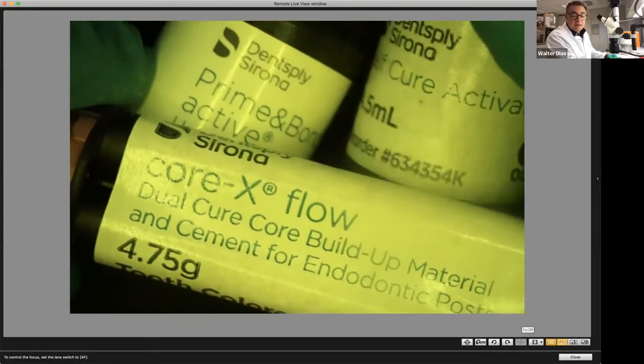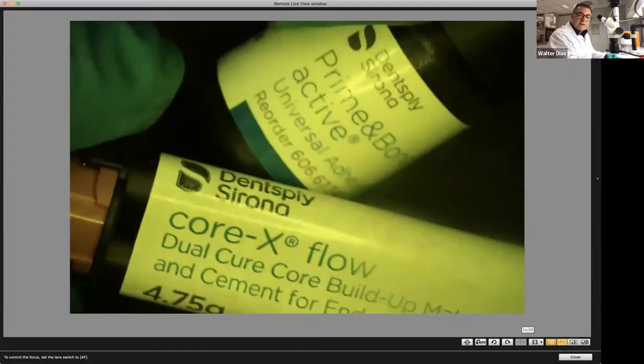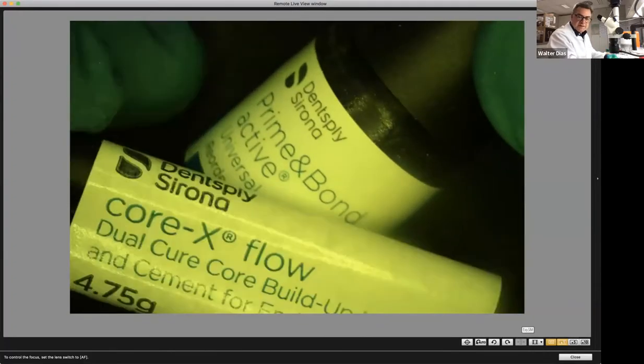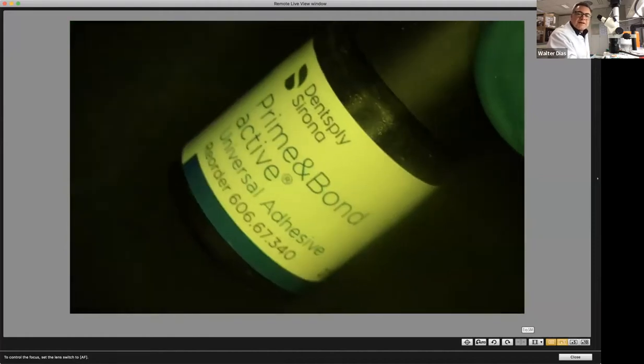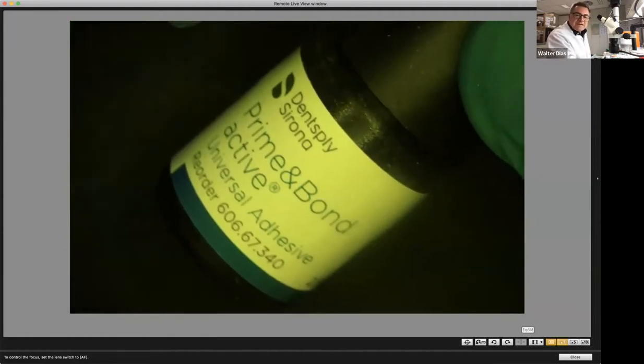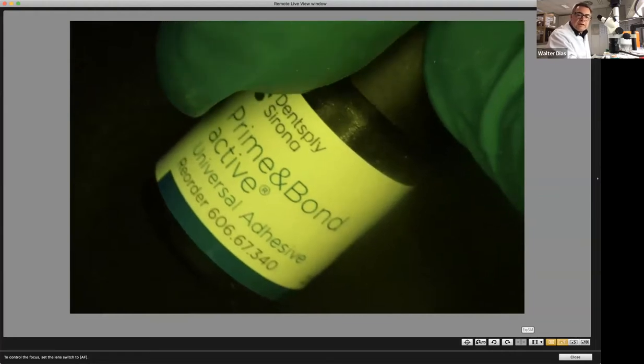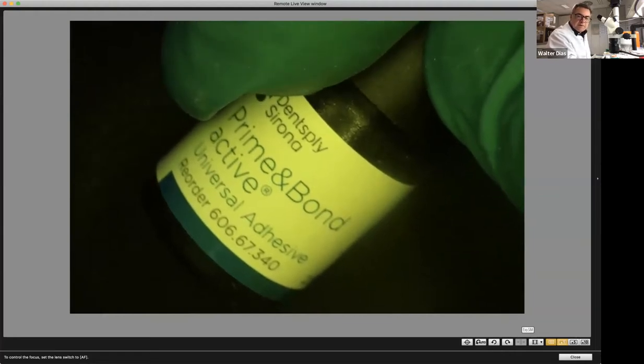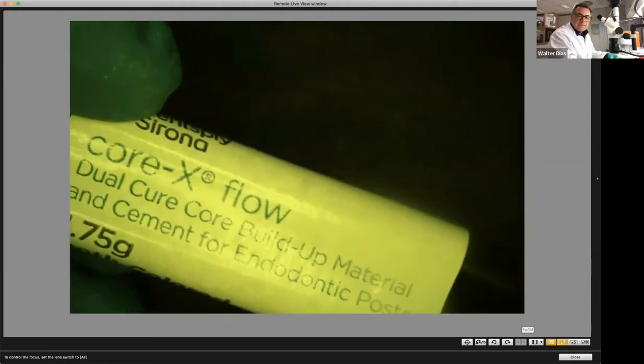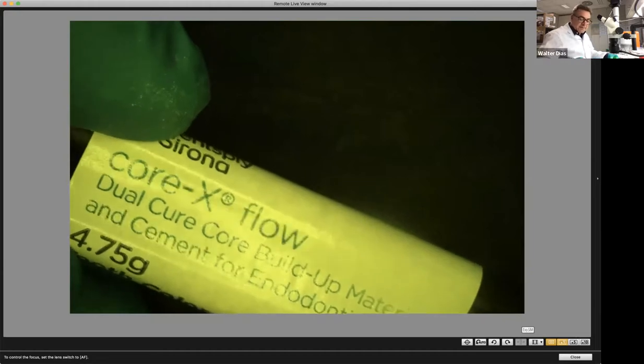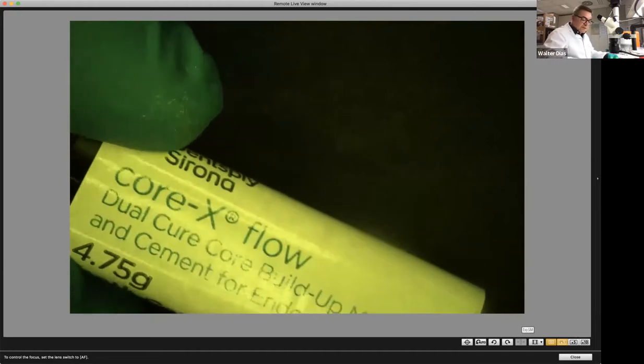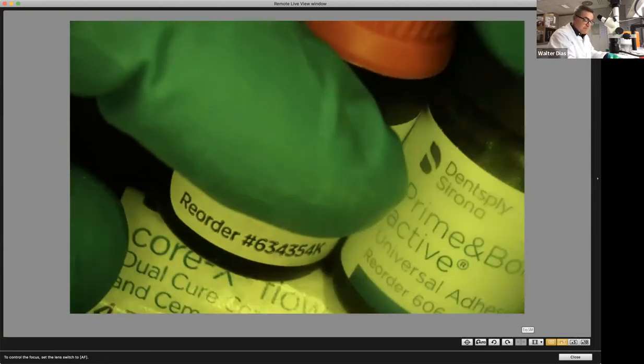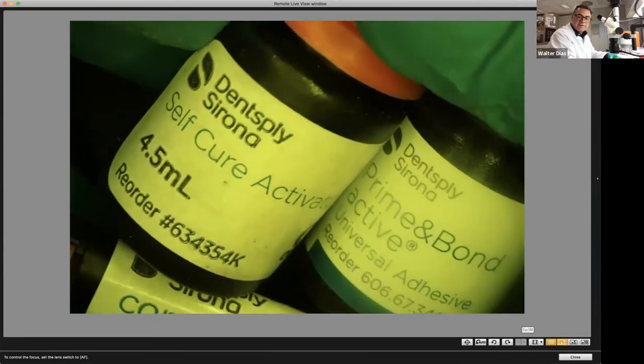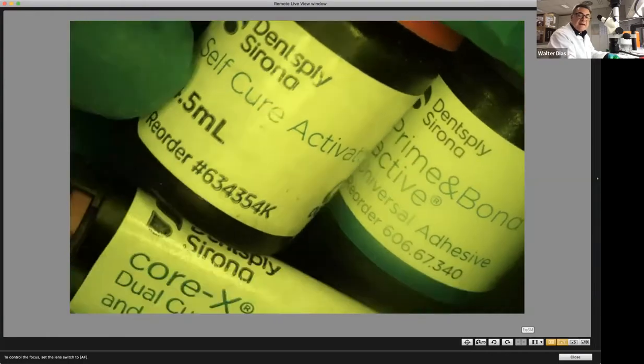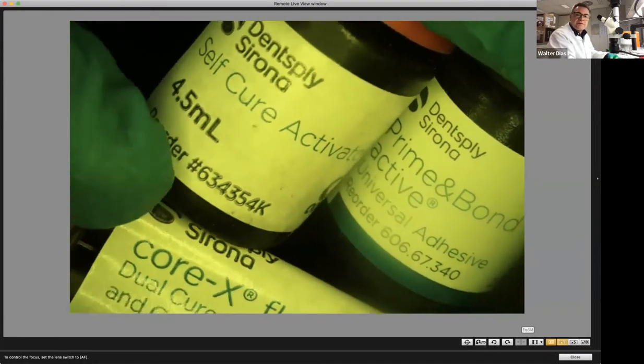When you're using Calibra, a regular resin cement, you use only Prime&Bond active, and you have to pre-cure the Prime&Bond active before you cement. But if you're using Core X Flow, which is a dual cure cement, what you can do is mix Prime&Bond active with the self-cure activator. And then you don't need to pre-cure the adhesive.